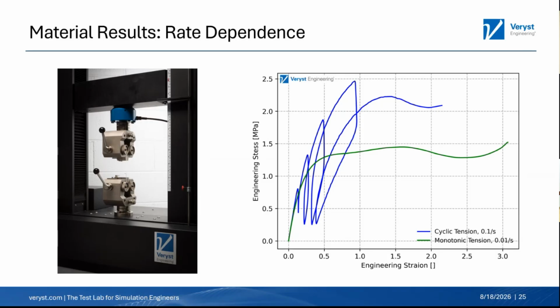And here you can see the time effect or the strain rate dependence that we see in this material. So the blue curve we did at 0.1 strain per second, so we get to 10% strain in 1 second. So it's a moderately fast test. You can see there that's what we had previously. That peaks at about 2.5 MPa. And then the green curve is what happens if we go an order of magnitude slower.